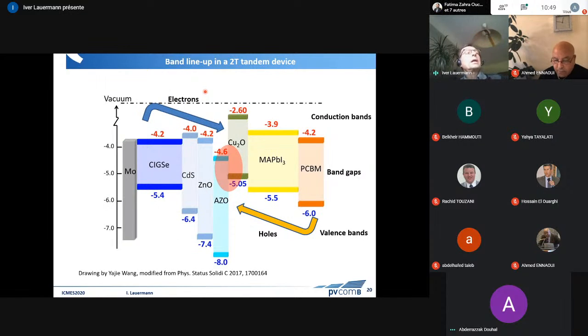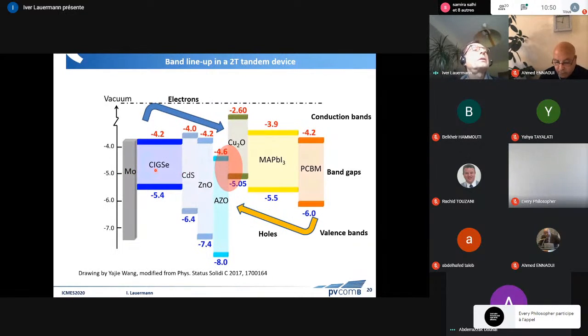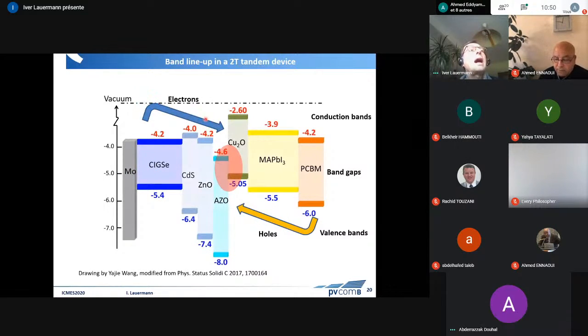So when we look at the energetics of this cell, here we have the energy versus the vacuum energy, energy of the electrons. This is our bottom cell, the CIGS, small band gap. This is the back contact. And now we have to build the stack in a way that the electrons from this cell travel down towards the recombination junction, and the holes in the top cell travel the other way towards the recombination junction.